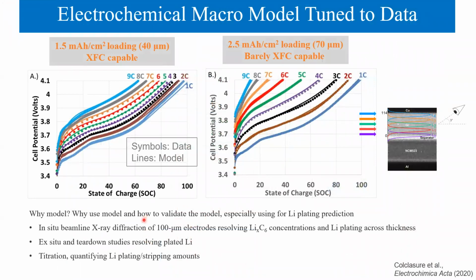In the DOE Extreme Fast Charging Program, a combination of cell testing and electrochemical thermal modeling is used to investigate the fast charging performance of cells with a low loading of 1.5 milliampere hour per centimeter square and moderate loading at 2.5 milliampere hour per centimeter square.